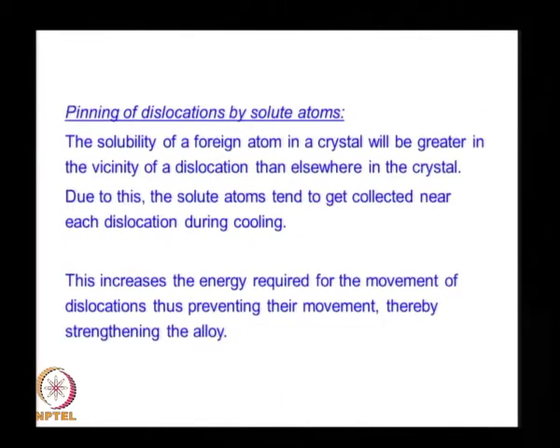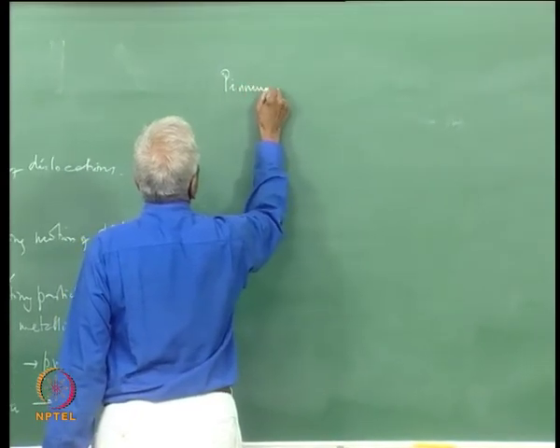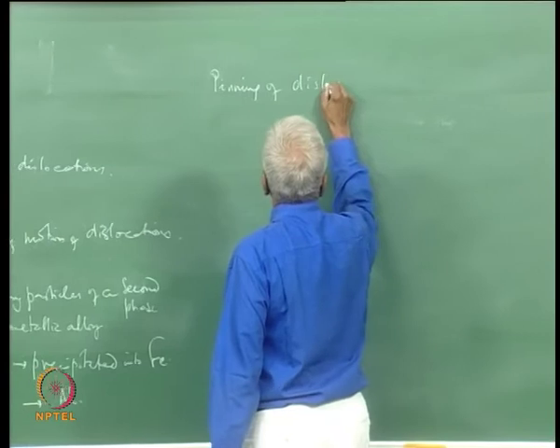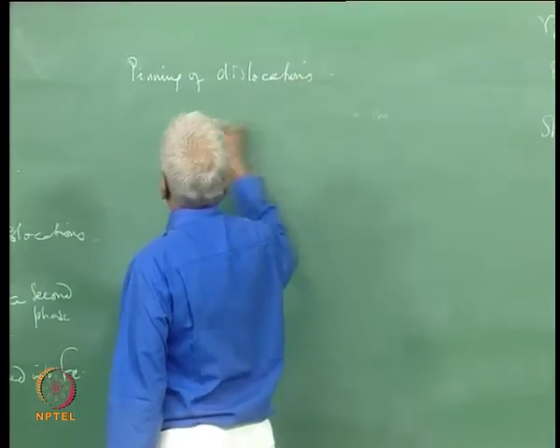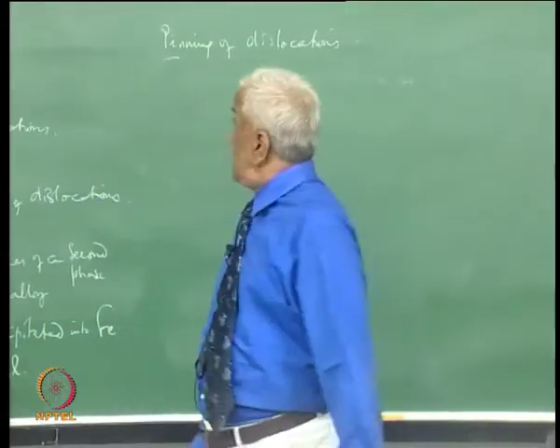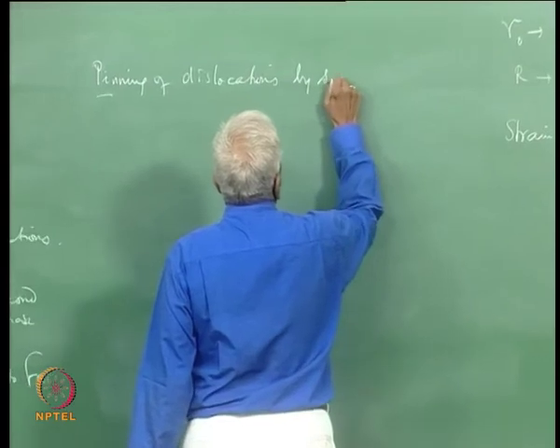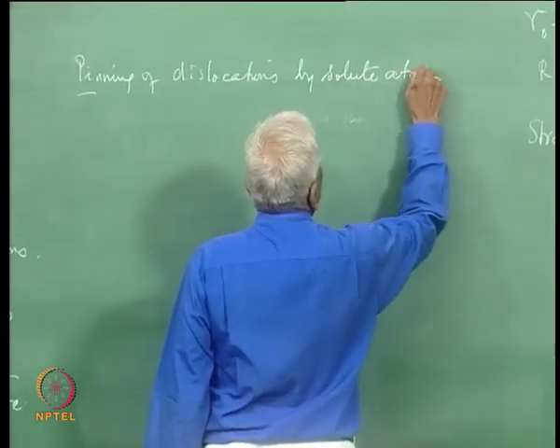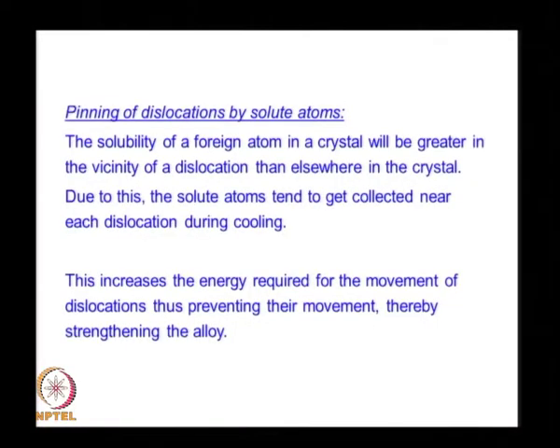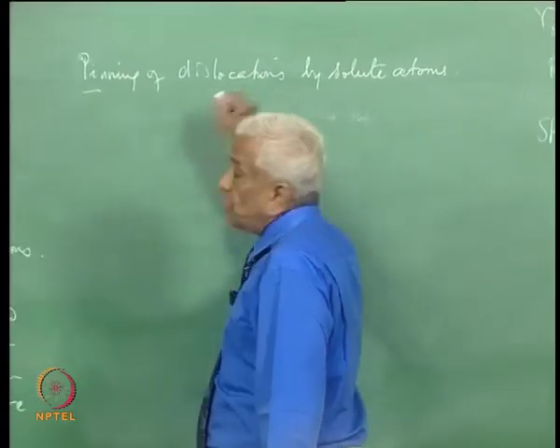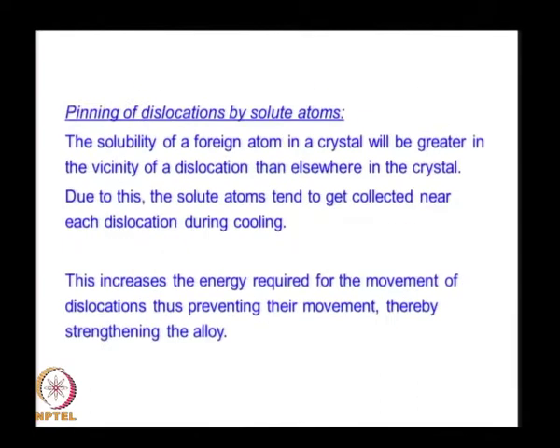Yet another method is to pin the dislocations. So, this is another method, by solute atoms. The solubility of a foreign atom will be greater in the vicinity of a dislocation than elsewhere. Therefore, the solute atoms tend to get collected near each dislocation during cooling. So, this increases the energy required for moving the dislocation, thus preventing their movement. So, that is called the pinning. So, this strengthens the alloy.